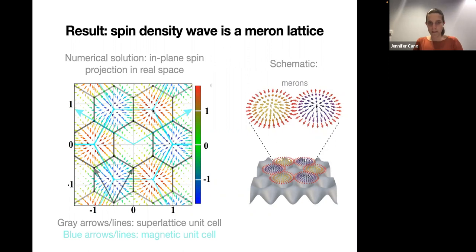So the color in this plot is telling you about the Z component, or the out of plane component of spin. And the length of all these arrows is telling you about the in-plane component. So like here, what we see is that we have a spin which is, say, pointing out of the plane, and then it smoothly interpolates around to the boundary where the spins are pointing pretty much in the plane. And then you move to another unit cell and it's pointing into the plane. And then again, smoothly interpolates to a bunch of spins that are pointing in plane. And so each one of these things is a meron, and they form this superlattice.